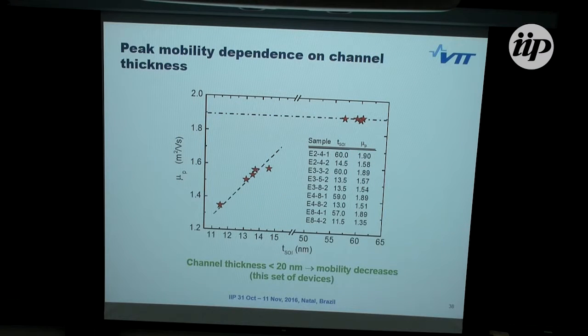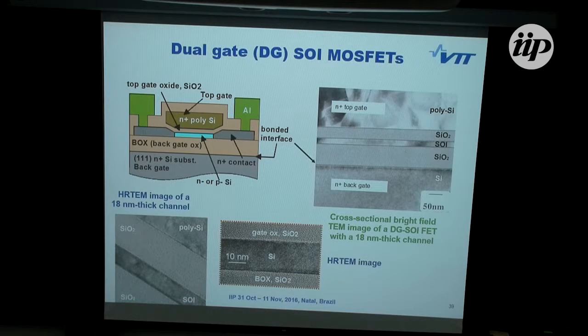And if we plot these peak mobilities for this set of samples, we see that when the channel thickness is around 20 or below, we start to see the decrease. But above 20 nanometer, there's no effect on the mobility. The effect here is not that drastic, so it's still quite good quality of transport. To make things more interesting, we use dual gate or double gate devices, which are otherwise similar. There's a top gate and channel, but the substrate is now a highly doped silicon wafer, and we use this highly doped wafer as a back gate. This is how it looks: polysilicon gate here, channel, and back gate. Again, there are some high resolution TEM images, and the quality of the interfaces is quite nice.